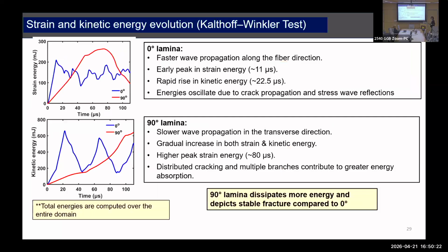So we continue and try to extract many different quantities. For example, I'll show here the global strain energy and the kinetic energy for the whole domain, not just locally where the crack propagation is happening, but for the entire domain. And if we compare between 0 and 90 degree lamina, we see a very similar tendency to what we have seen in the crack profile picture.